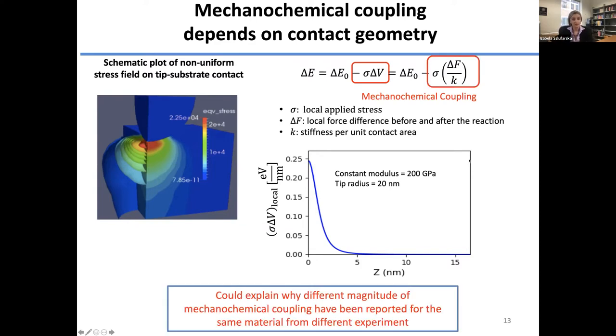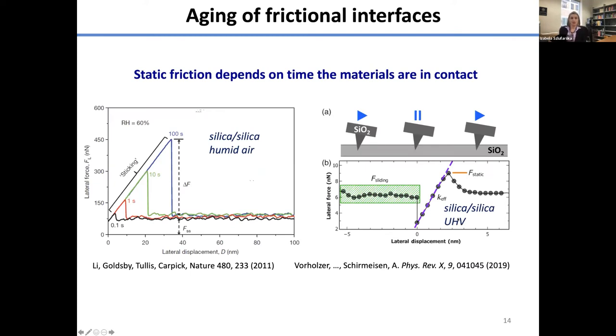So we believe that this is one of the reasons why experiments performed on nominally the same systems, in this case silica, but also in other examples, have reported a very different magnitude of the mechanochemical coupling: because the bulk contributes, and because the stress distribution in the bulk that comes from the contact is going to play an important role.